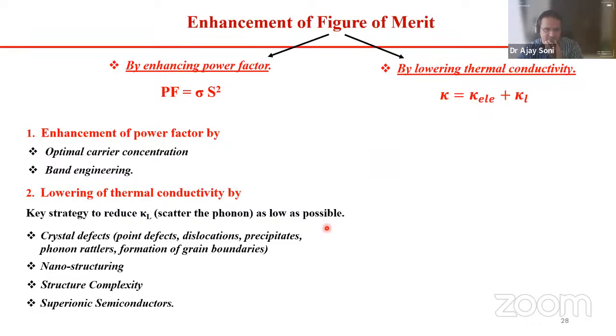of the solids. Okay. So what you can do is you can enhance either this one, or you can reduce this one, or you can bring this one to as minimum as possible. And how you can do that is you can create crystal defects, point defects, dislocations, precipitates, or phonon rattlers, or there are multiple scattering centers you can create by nanostructuring, or you choose a material which has a structural complexity or the superionic semiconductors, so that you independently reduce the lattice part, because controlling these two will require control of this one also. So which means if you can minimize this one, you can actually have the optimization of that.